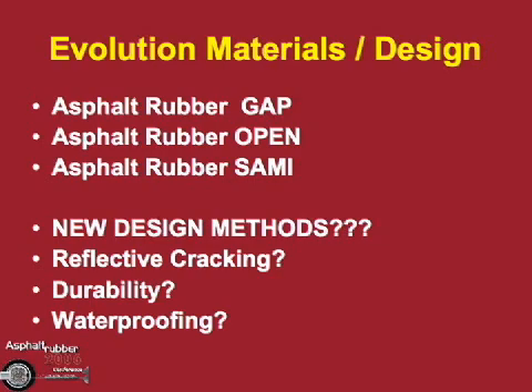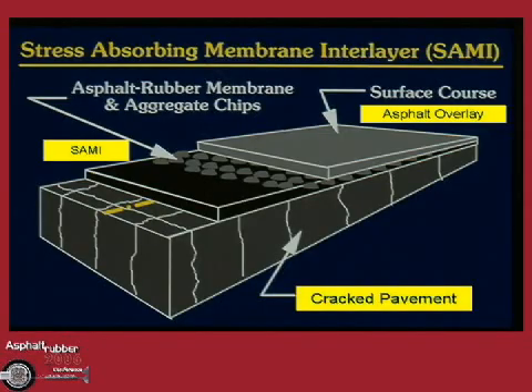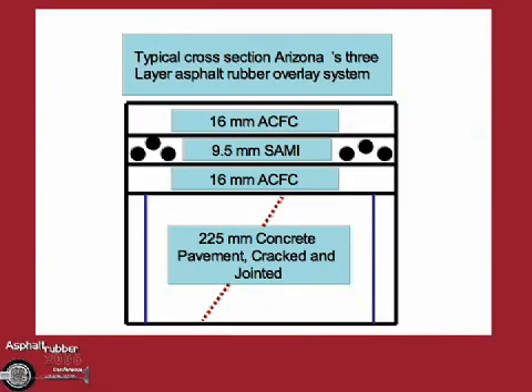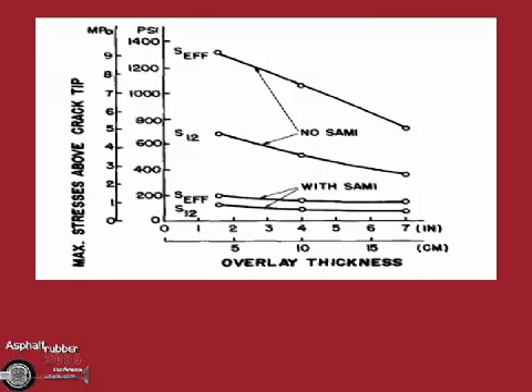So we know, and it has been well reported, that SAMIs, like Dr. Shatnawi said, work great. Now, how do we incorporate this "work great" in our knowledge? How can we push the limits? And how can we also incorporate the limits that are given to us by these two, gap-graded and asphalt rubber mixes? Arizona started doing some tests many years ago, and they tried new concepts to resist reflective cracking by putting asphalt friction courses, then a SAMI, then asphalt friction courses, trying to make it waterproof, trying to make it crack resistant, and they actually did finite element analysis at the time. And look at this. They realized that the stress at the crack tip with SAMI and no SAMI was tremendously different.